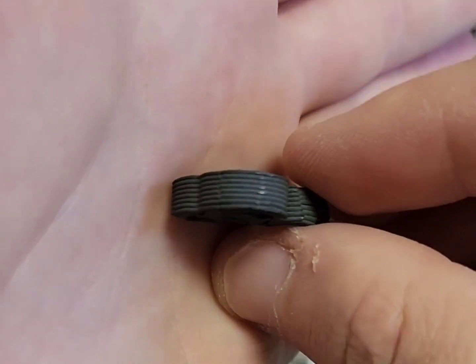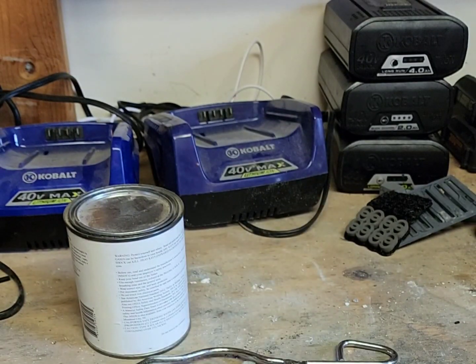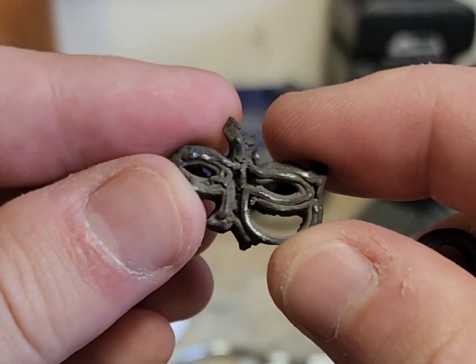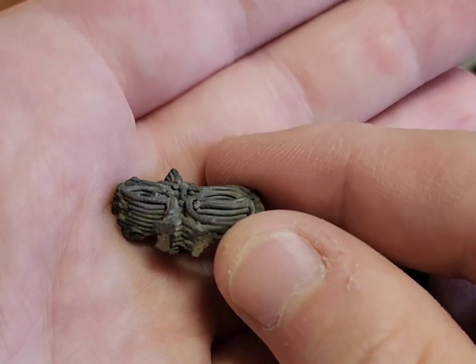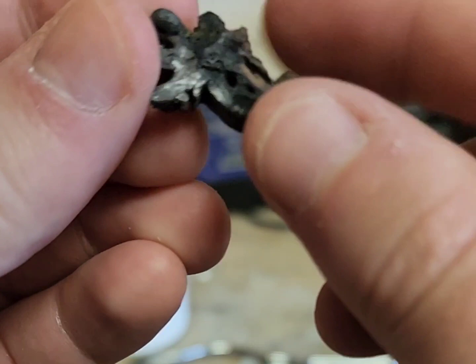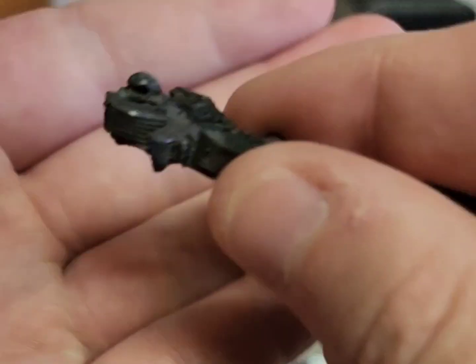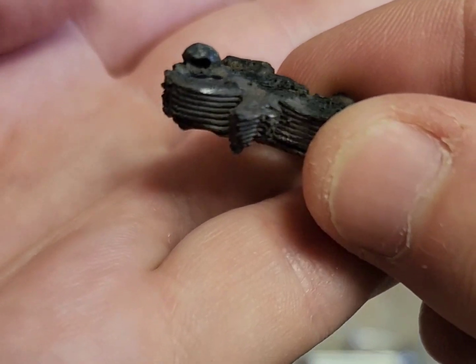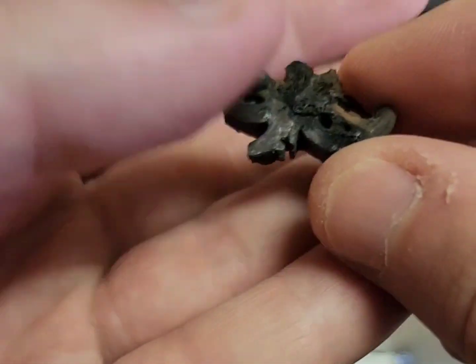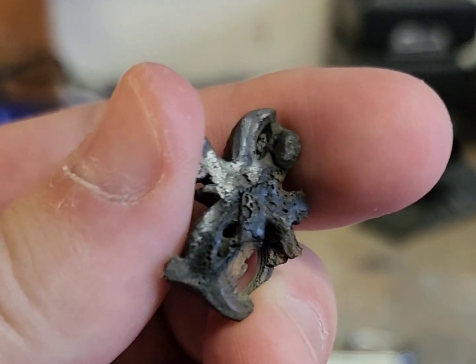If I was to polish each side here, this portion would polish, but this portion here throws sparks. Another piece from a different run had some interesting shrinkage somewhat in the center. I broke this one up, but the back side polished a little bit as well. You can see some beading of titanium right there, which shows me a bit too high of temperatures for the center cycle.